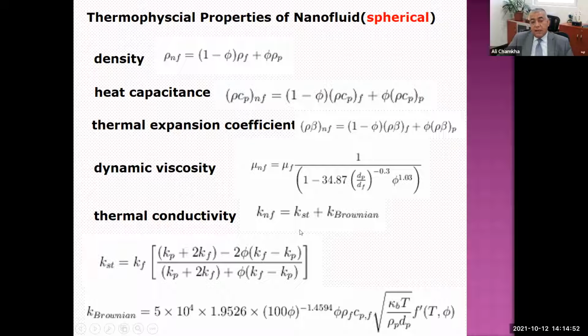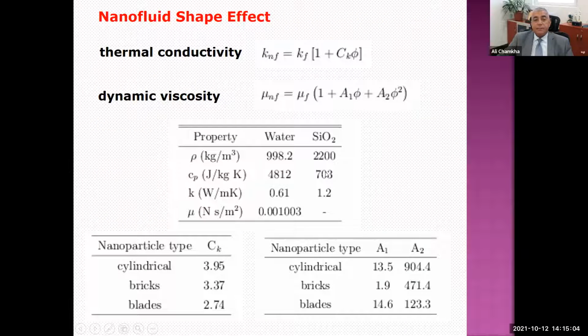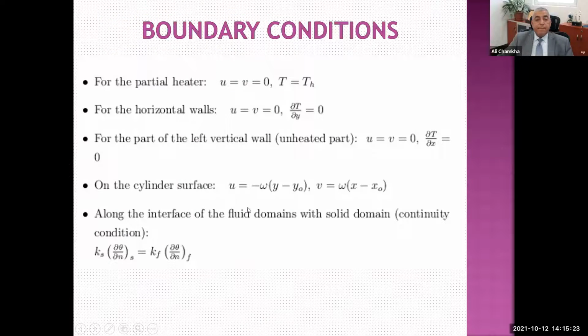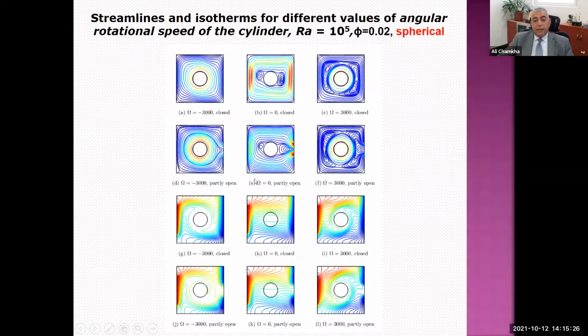This is the Brownian part, because here the thermal conductivity for the nanofluids is the static part and the Brownian part, and these are added together. Again, the dynamic viscosity here is different. We have used a linearized thermal conductivity model like this that's based on the shape. So the shapes that we considered were cylindrical particles, bricks, and blades. I'll go directly to the results.